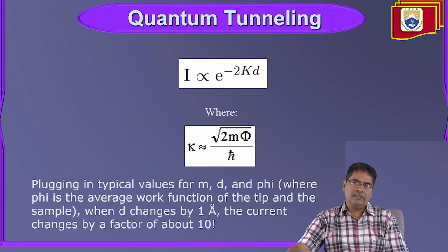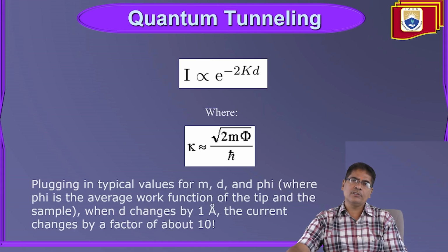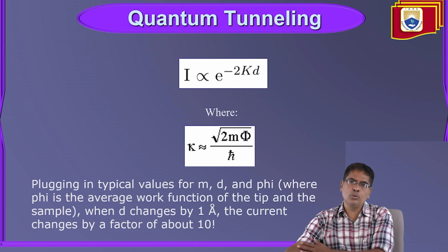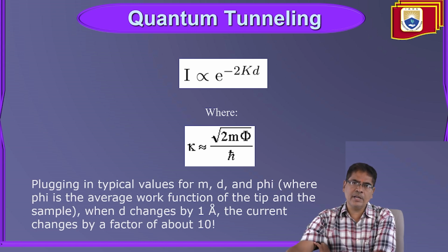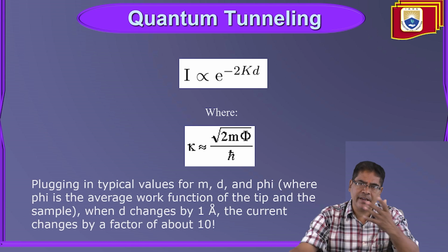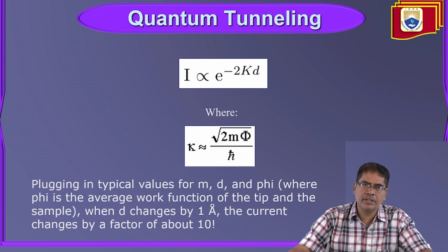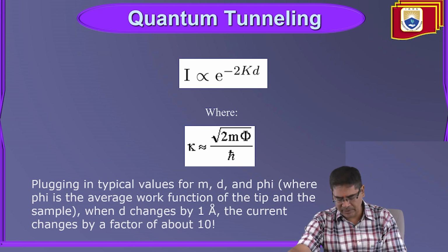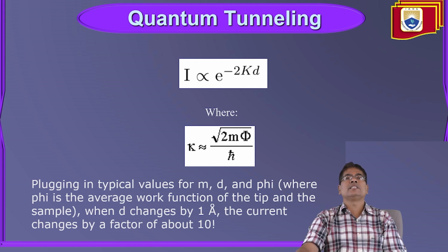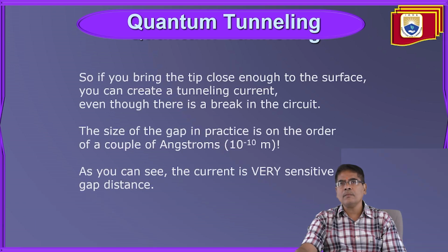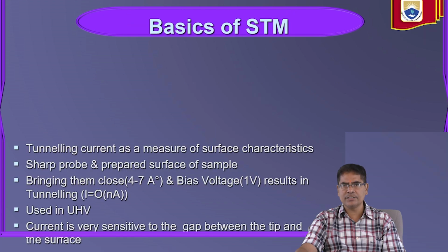So the quantum tunneling case is given by I proportional to e power minus 2kd, where k is approximately the square root of 2m phi by h. Plugging in typical values for mass, d and phi, where phi is the average work function of the tip and the sample, if the distance changes by 1 angstrom, the current changes by a factor of about 10. So if you bring the tip close enough to the surface, you can create a tunneling current even though there is a break in the circuit. The size of the gap is on the order of 10 power minus 10 meters, right? As you can see, the current is very sensitive to the gap distance.